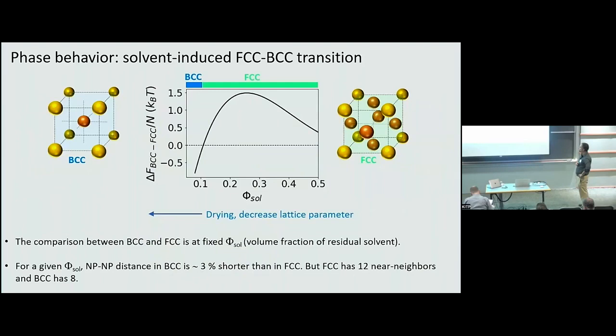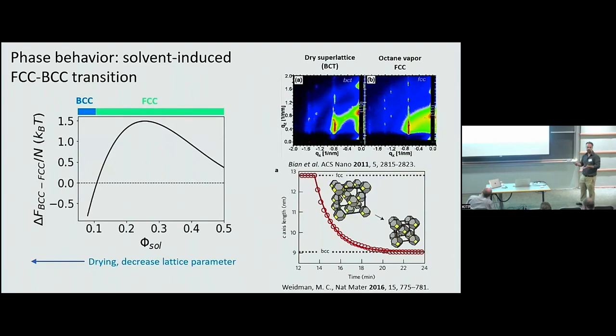And this is thermodynamics. This is basically a plot of the difference of free energy between BCC and FCC as a function of the amount of solvent in the system. Because there is an incompressibility constraint, as you decrease the amount of solvent, the superlattice should shrink, so the lattice parameter should decrease. And here I will always show you some bars showing which structure is the stable one in different conditions. So what we get here is a transition from FCC. This is a prediction of the theory. It's a transition from FCC, where the superlattice is swollen with solvent, to BCC when it's not. And that's basically what they found in the experiment. So this transition, we get it okay.